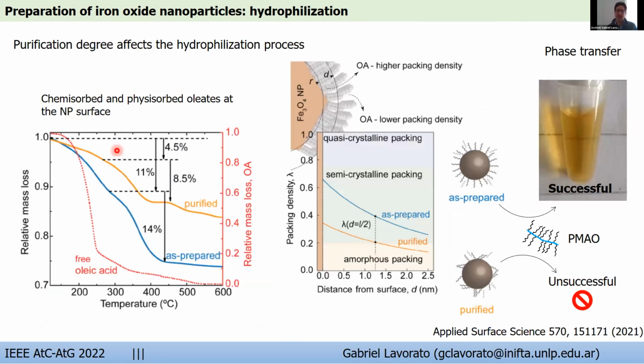So it was quite surprising that the hydrophilization method was not successful for every particle batch, and nanoparticles with different purification degrees after the synthesis show different results. And we were able to correlate the packing density of the oleate capping at the surface, which was obtained from thermogravimetric studies, to the success of the hydrophilization process. And we found that below a certain packing density, the hydrophilization process is no longer possible, although the particles can still be dispersed in non-polar solvents. So there is an optimum range for the oleate capping to achieve this hydrophilization process.